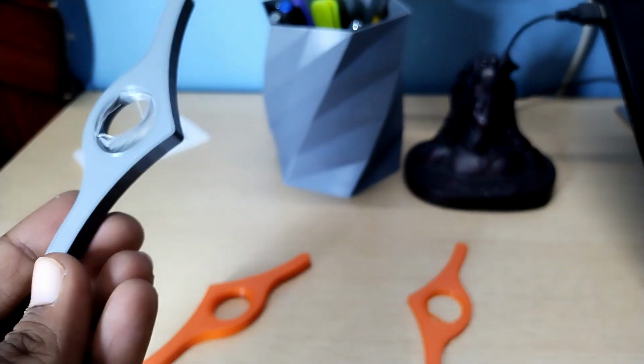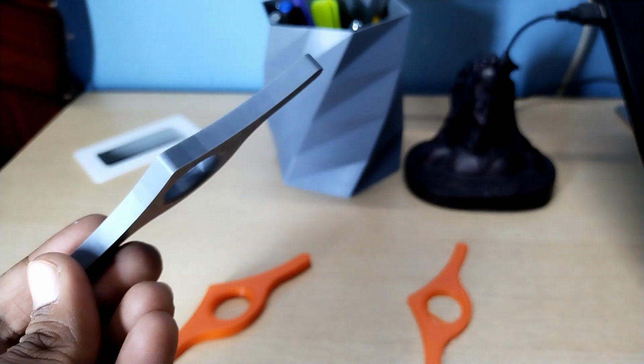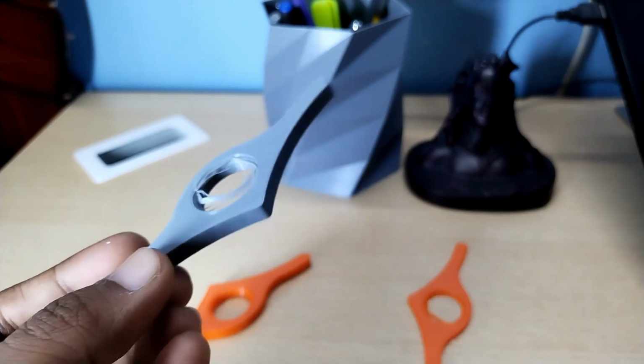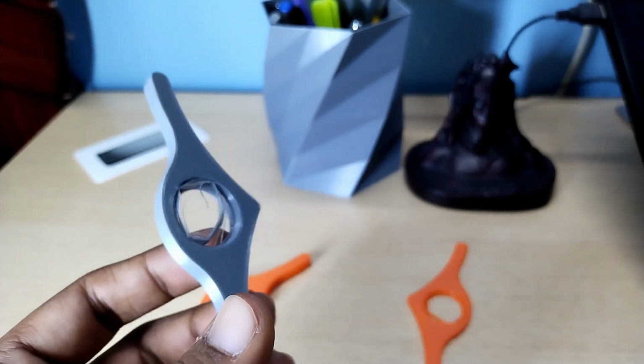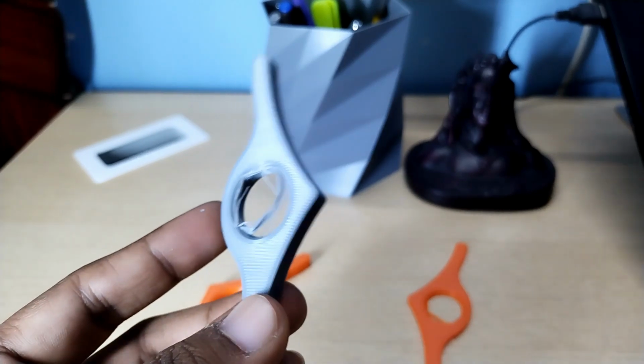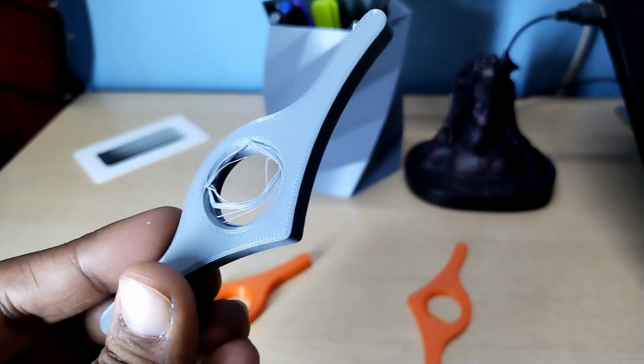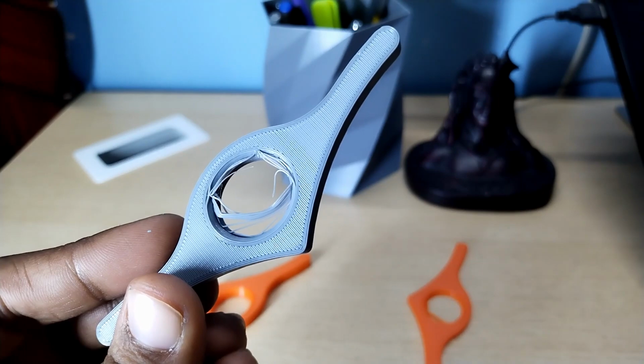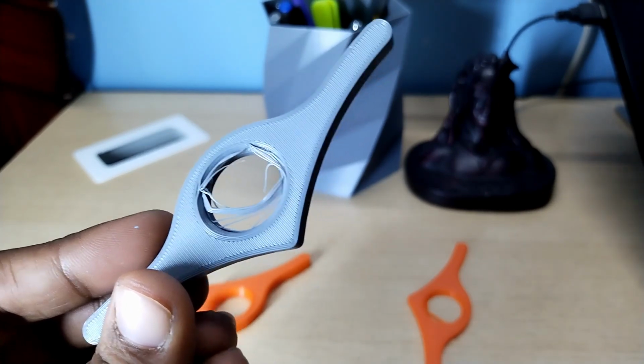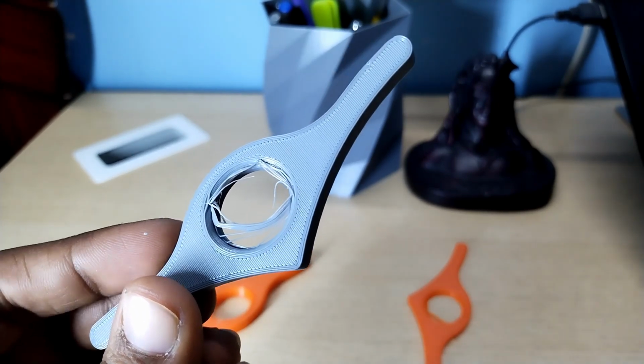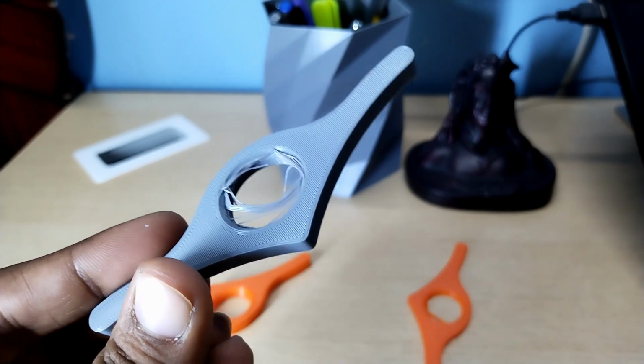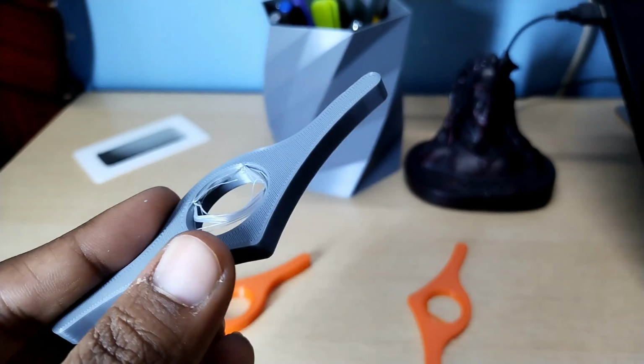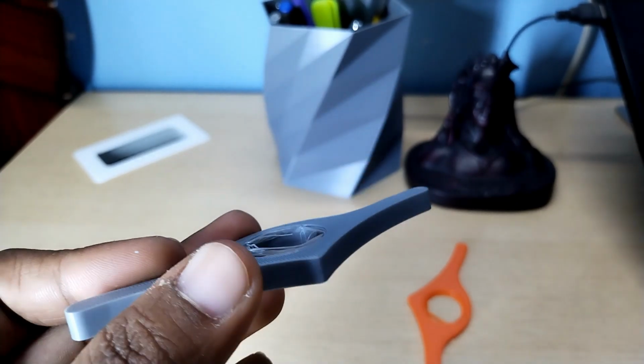So what causes this delamination? Simply, there are a few factors which cause this. First one is not enough temperature of the nozzle, and second, print speed of walls is too fast. Wall overlap is not set right. And the last is retraction distance. Also, there are a couple of other factors which affect it, but I don't think they affect that much.